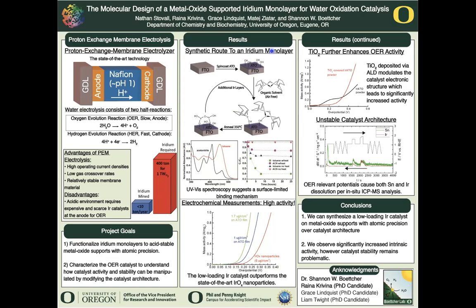And to do this, I developed a synthetic route to an iridium monolayer. You have a metal oxide substrate, and then you spin out another metal oxide, in this case, antimony doped tin oxide, on top to increase the catalyst conductivity. And then you can actually take this iridium COD dimer here and soak it in organic solvent in air-free conditions and mount iridium onto the surface of your metal oxide and then anneal to remove your organic ligands, giving you this ultra thin iridium catalyst.